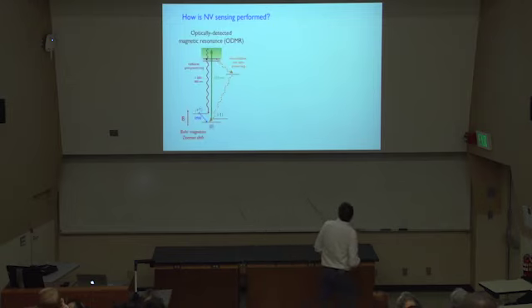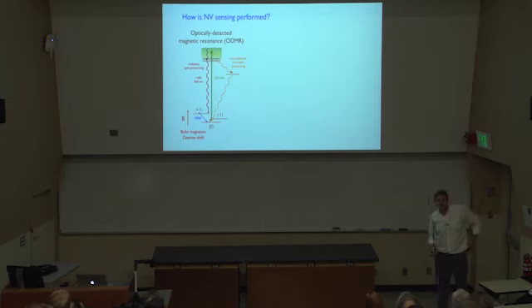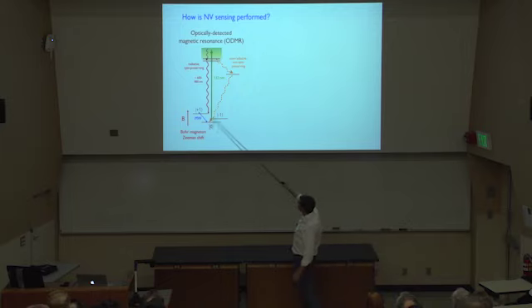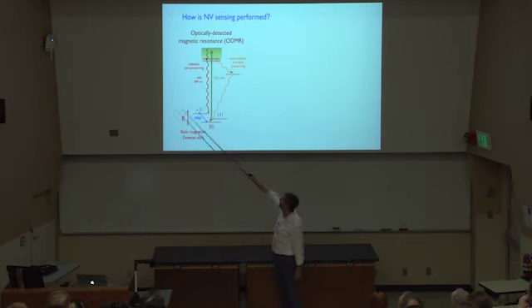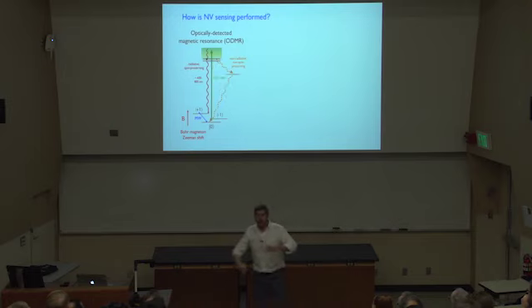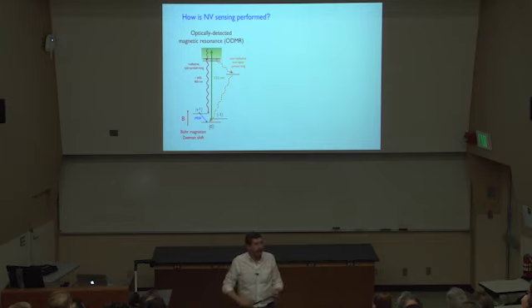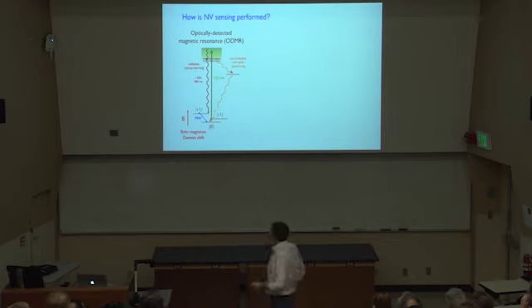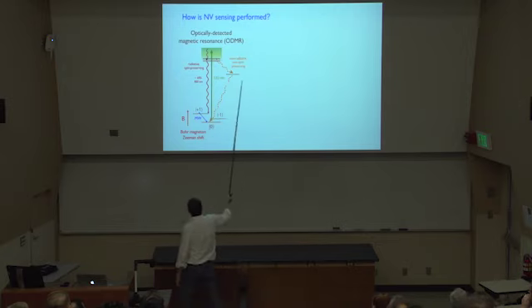So how's the sensing performed? Let's look at the energy level structure, the energy levels that matter for the NV, and it's shown here. You have the ground electronic spin states, and you have the electronically excited states, much like an atom, but of course it's inside the diamond lattice. Both for the ground states and the excited states, there is a vibronic band on the order of 100 nanometers in wavelength. So the energy levels can be moved around by the thermal phonons inside the lattice, but those vibrations affect the spins very little. So the energy levels are shifting around randomly, but the spin states are not affected by that sort of thing. There are also some metastable states indicated here.